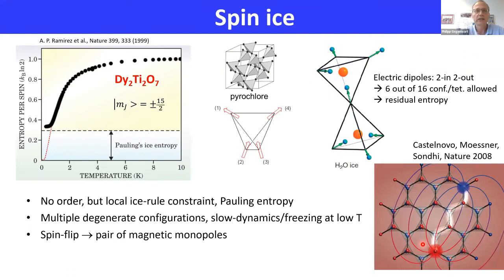So I'd like to start with a brief reminder on the physics of spin ice. In a certain class of pyrochlore-based rare earth oxides, we have the magnetic moments placed on the corners of tetrahedral units, and the single ion anisotropy dictates that the magnetic moments can only be aligned towards the center and outwards from the center of the tetrahedra. The lowest energy states are those 6 out of 16 configurations where always 2 spins point inwards and 2 spins point outwards, and that's the famous spin ice rule.